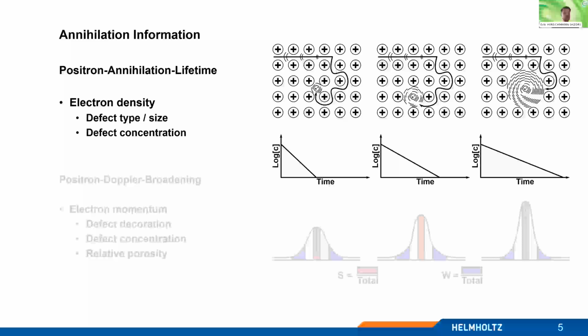So what information do we get from the positron? We have mainly two kinds of properties we measure. First of all, the positron annihilation lifetime, which is more or less the time difference between the birth and the annihilation. And this helps us to investigate the electron density at the annihilation site. And this refers to the defect type, size, or the defect concentration. And the grayish part I will show you later after or within the discussion of the devices we use.